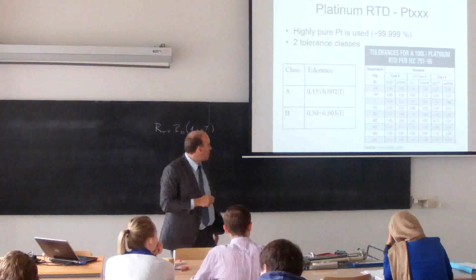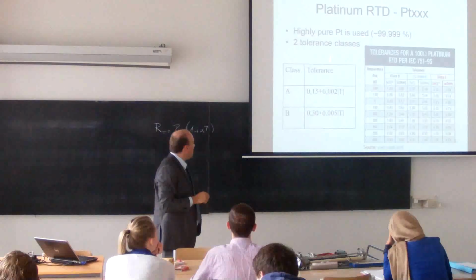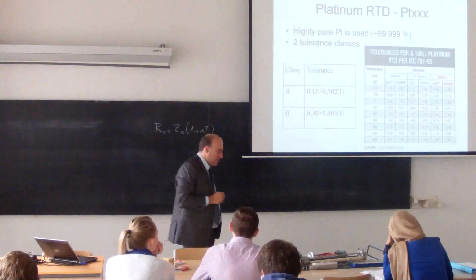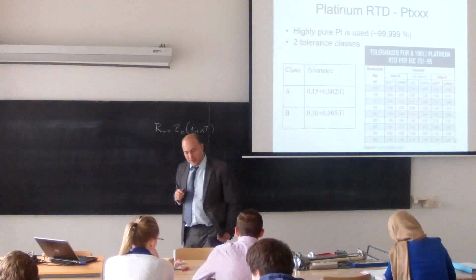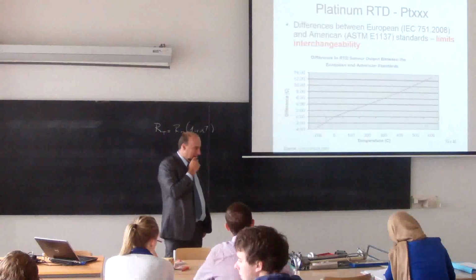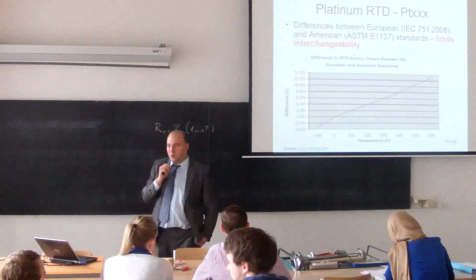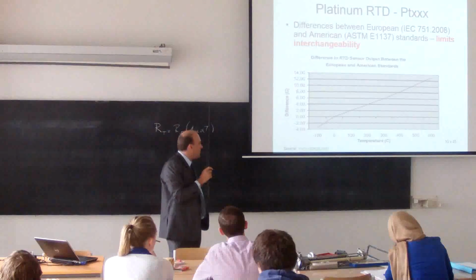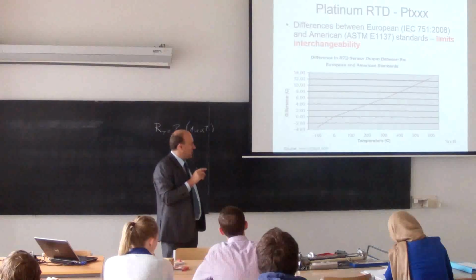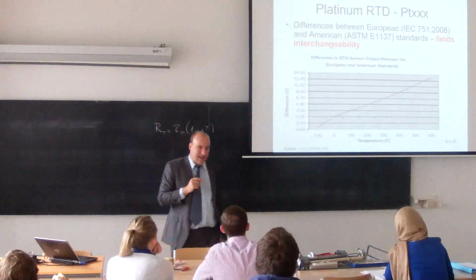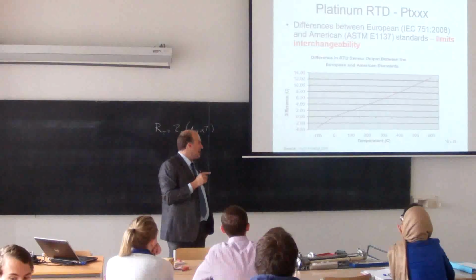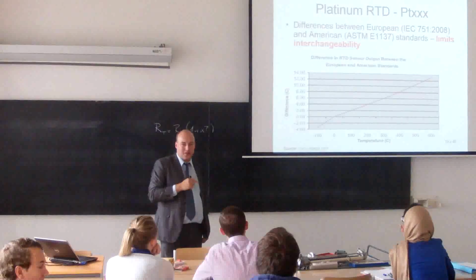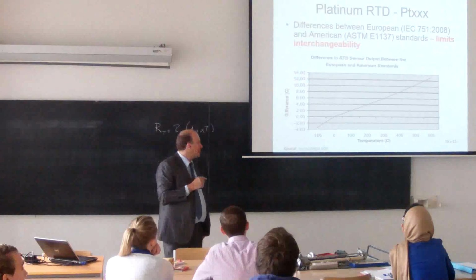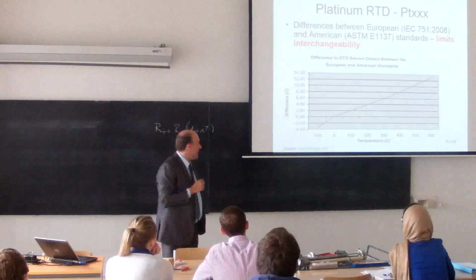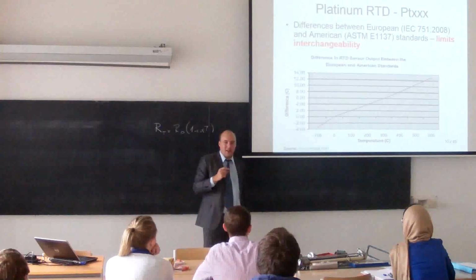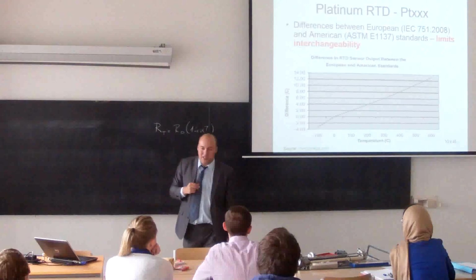However, it's not so easy. We have class A, class B. Both classes are produced from very pure platinum. When you buy such a sensor, you need to be aware that there is a difference between the European standard and the American standard. They are all different standards, and you can't really use a sensor made to the other standard. Why? Because there is a difference in the purity of platinum, and it will give you a difference in temperature reading. And it's not insignificant.